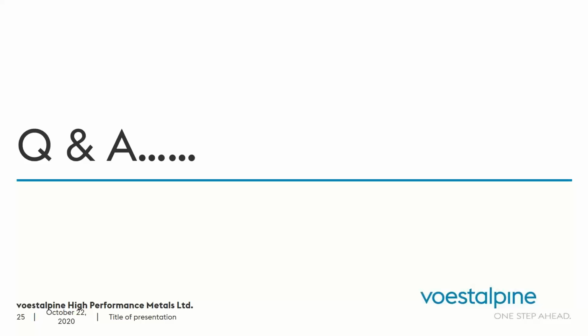Bottom line is that coatings will not fill in machining marks because you're only talking 4 or 5 microns, and machining marks can probably be measured in thousandths or tenths. So provide the smoothest possible surface to your coater that you can possibly do in-house, and then consider coatings like gasket groove inserts, very fine details. Give it a high polish in those areas, coat those areas, and then that will prevent the details from breaking out. Hope that helps.